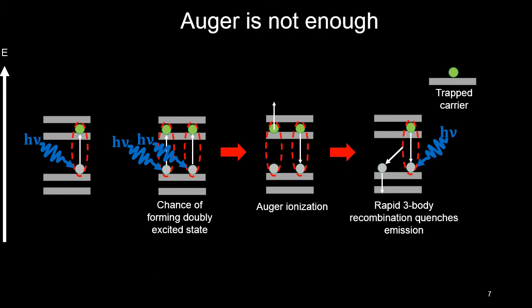It turns out that this phenomenon of randomly switching between on and off states has been known for quite a while, but the mechanism remains unclear. One of the earliest proposed mechanisms, and certainly something that we can concur as part of the problem, is Auger recombination. Even though we try to gently excite these things such that we only put one exciton into the dot at any given time, probabilistically we end up putting in two excitations.